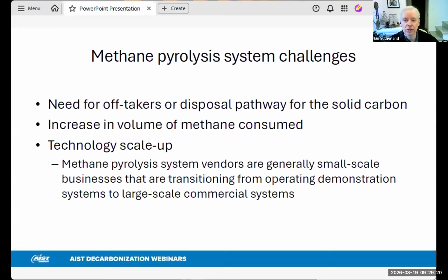However, there are some challenges in adopting methane pyrolysis for hydrogen production. Firstly, for every 1 kilogram of hydrogen that is produced from the process, 3 kilograms of carbon are produced. And this means that large-scale carbon off-takers will be needed when the system size scales up. And this also will involve handling and transportation costs. And secondly, the process does consume more methane than steam methane reforming. So this increases its operational cost in comparison to steam methane reforming. And also it will increase the calculation of upstream fugitive methane emissions.